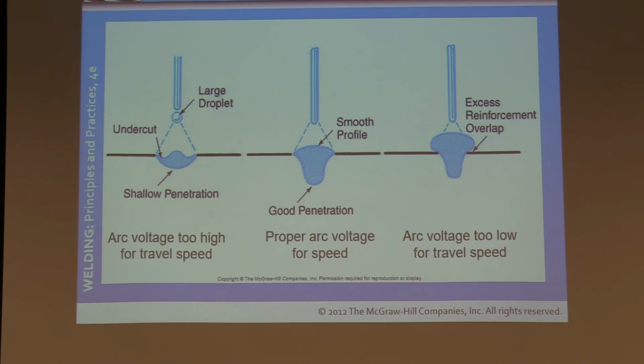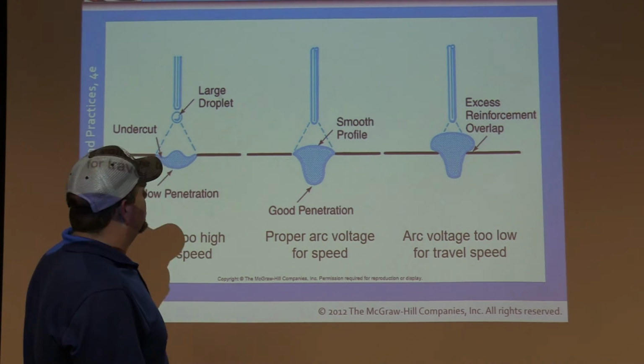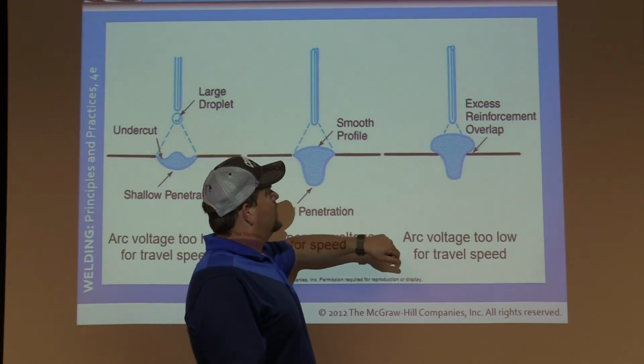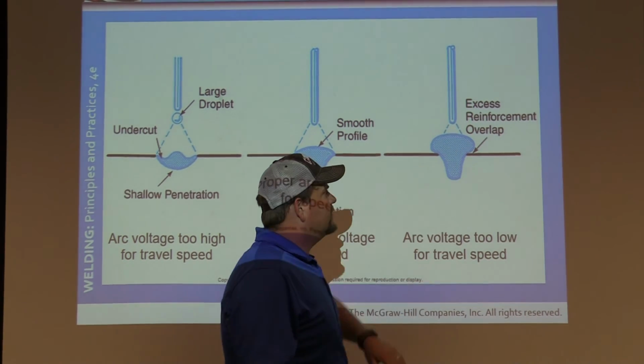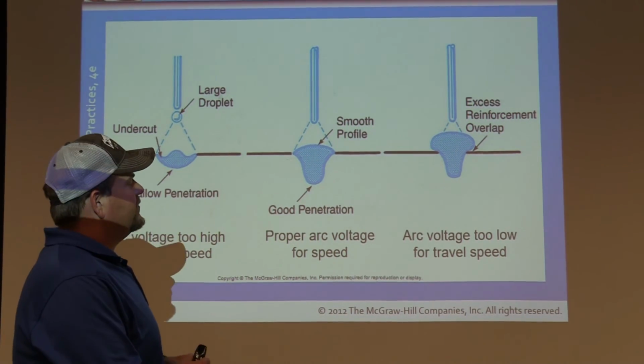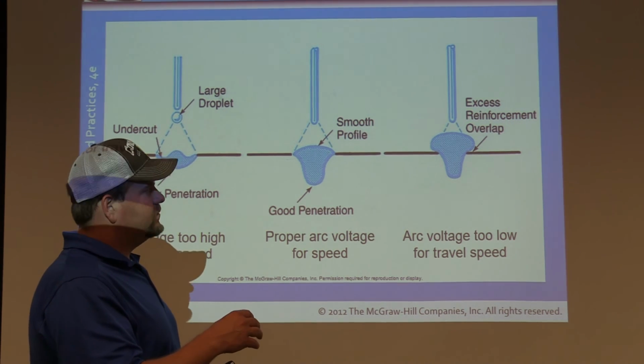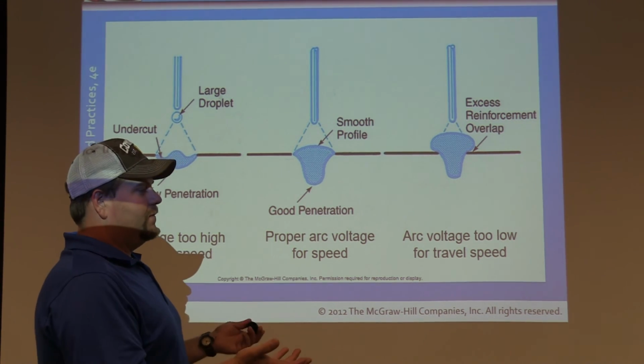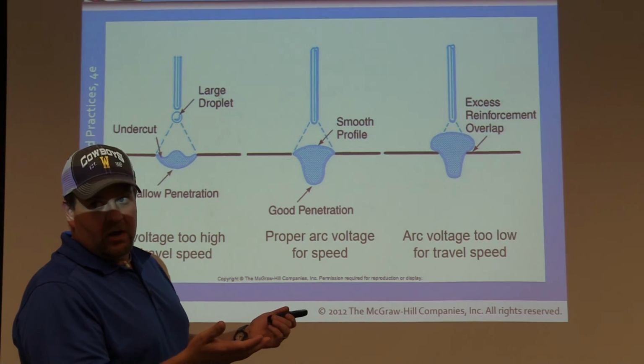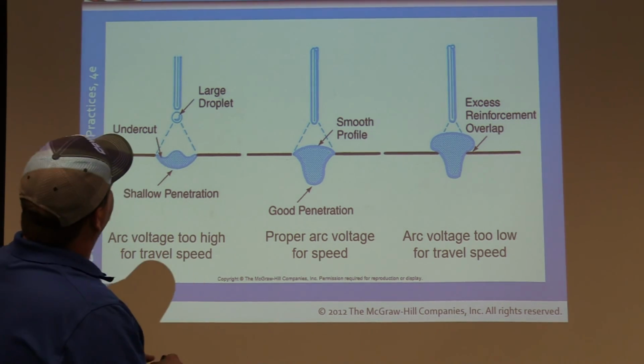Penetration comparisons, as you can see there on the left, shallow. Here's arc voltage is too high for the travel speed. You start getting a lot of undercut. This is when your wire speed's usually turned down low and your voltage is high. Not really the greatest profile. Here's what we're looking for. And then here as well, this is when your arc voltage is way too low and your travel speed is slow as well. You're getting a lot of excess weld. It's just laying on top, real high crown, and so forth.